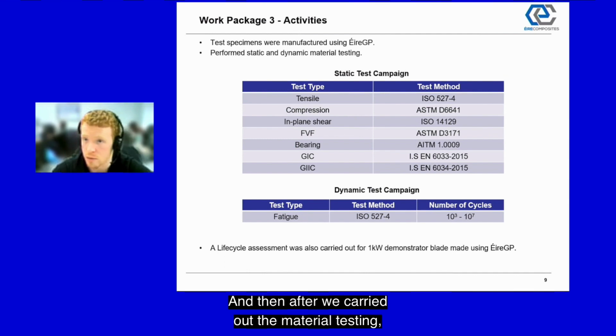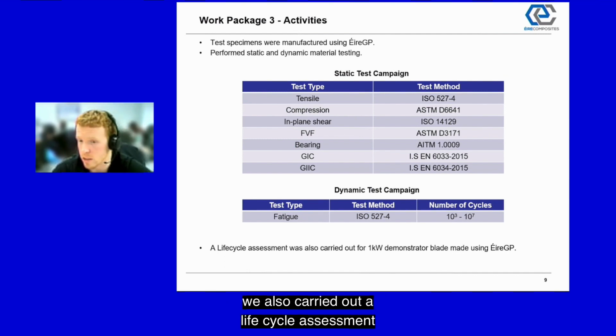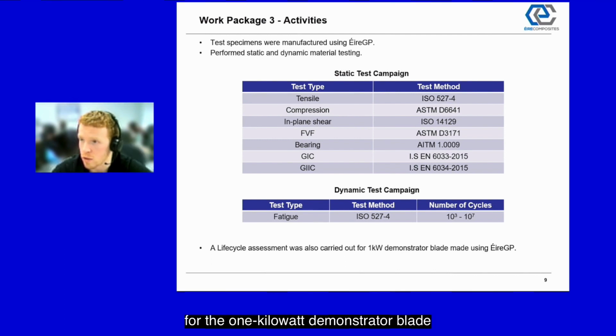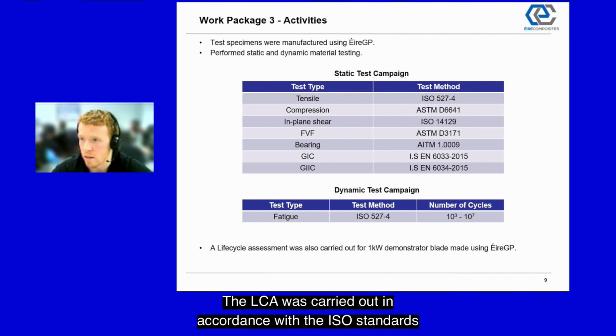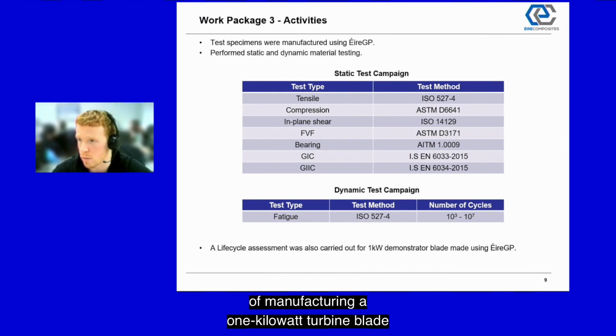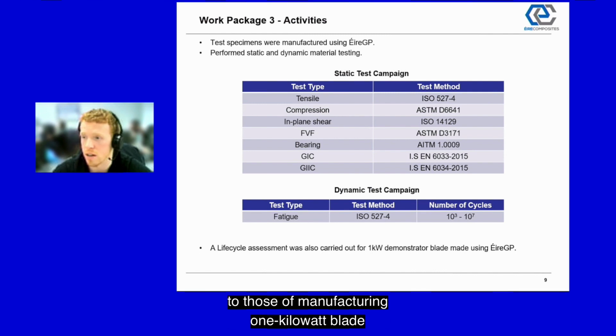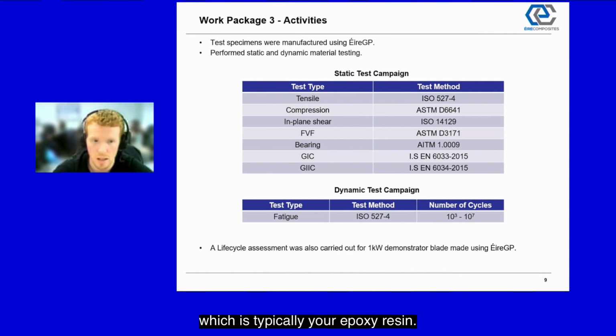And then after we carried out the material testing, we also carried out a life cycle assessment for the 1 kilowatt demonstrator blade which was made using the Eire GP material. The LCA was carried out in accordance with the ISO standards, and the LCA compared the environmental effects of manufacturing a 1 kilowatt turbine blade using the Eire GP material to those of manufacturing a 1 kilowatt blade using non-recyclable fiber reinforced plastic, which is typically your epoxy resin.